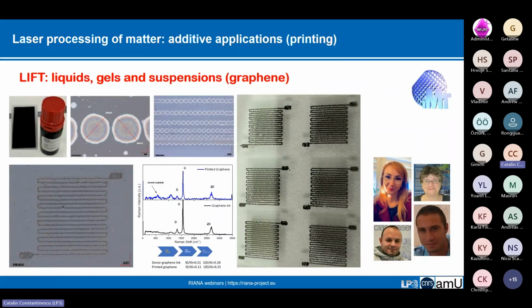Furthermore, as graphene is a particularly illustrative case, here we present a test we did a year ago with some colleagues from Bucharest as well, and this was a collaboration on how to print graphene inks. So we printed from commercially available inks. We did a drop cast donor sample. We printed first some droplets to understand how the LIFT process takes place. Then we controlled the overlap of the droplets, and then we printed various structures. These were used as resistors, as heaters for heating applications.